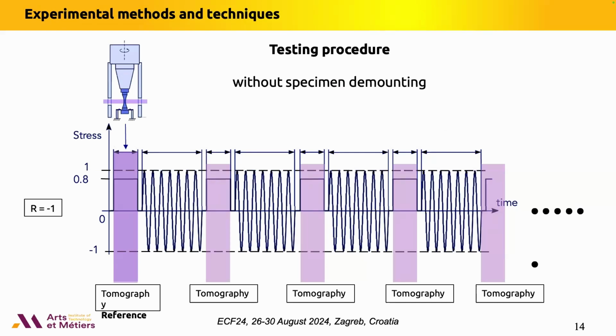And then step by step, we apply cyclic loading. So a first block is applied up to the detection of the internal crack initiation by the fast Fourier transform analysis of the velocity of the free end of the specimen. And then a tomography scan is done to obtain the image of the cracks. And then we run again a cyclic loading during a number of cycles that has been programmed. Then we observe again the increase of the crack and so on, up to either the breaking of the specimen or up to the end that you decide because, for instance, the stress intensity factor becomes too high.